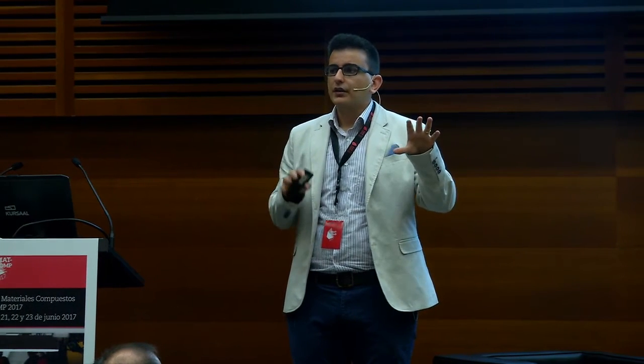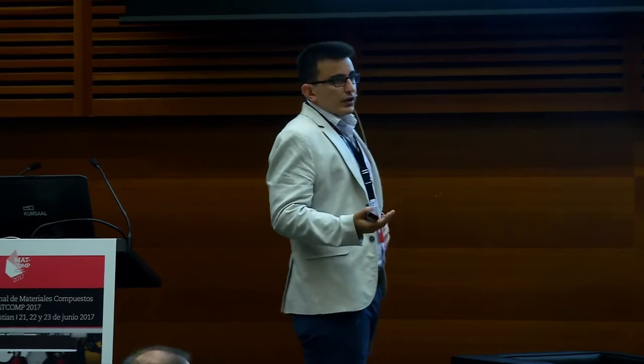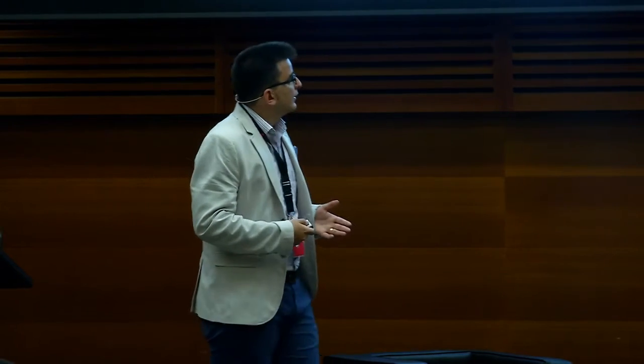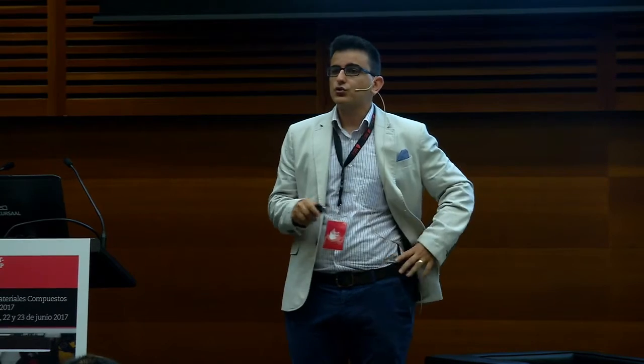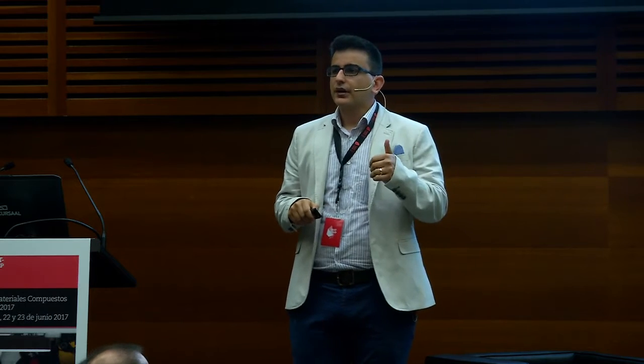So this is the picture of microscopy analysis and the image processing. We have only fiber and resin distribution now. However, the total pixel size is relatively too high for a finite element simulation. It's now 7 million pixels with a pixel size of 1.6 micron. So the idea is to average these pixels for a smaller number of pixels. After averaging, we have 24,000 pixels, which is doable with the simulations, and with approximately 25 microns, so approximately the diameter of one glass fiber, more or less.